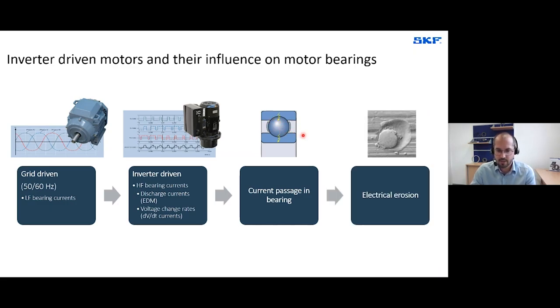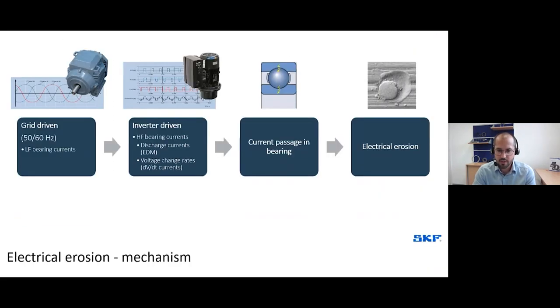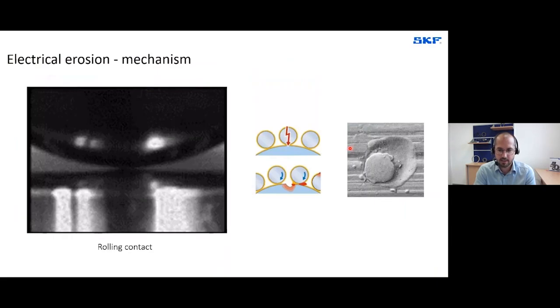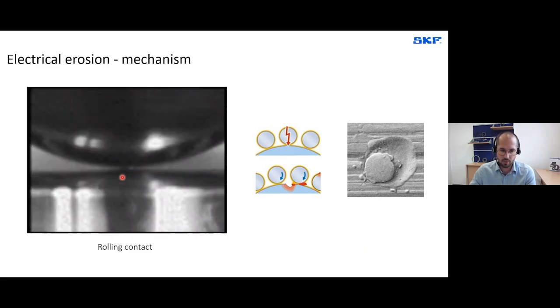we experience electrical erosion. And what is electrical erosion? It is basically a transfer from one bearing ring through the rolling element to the other bearing ring, as shown on the slide before. But the issue is that we don't have a perfect conduction between rolling elements and rings. Means there is sometimes, or hopefully always, lubricant between the components, which is an insulating material. And if the voltage potential is big enough, it can happen that there is sparking happening between the two surfaces, which we can see a bit on the left, where the ball is oscillating and the washer is standing still.